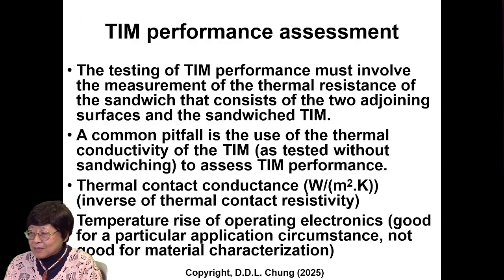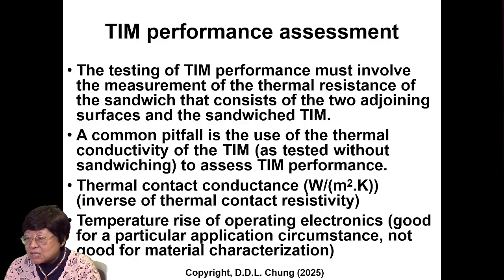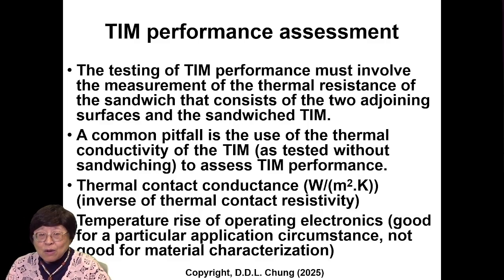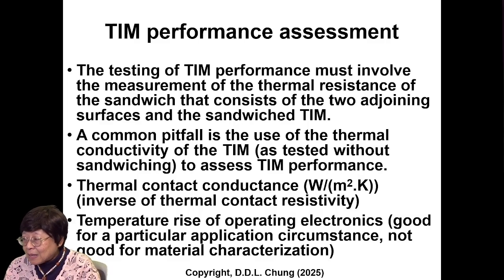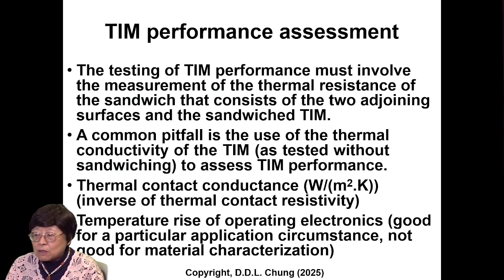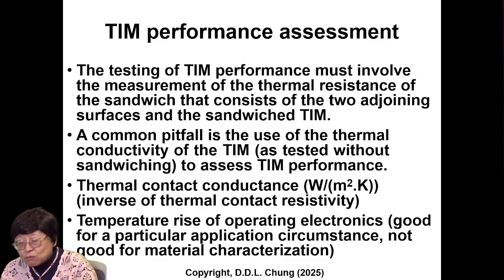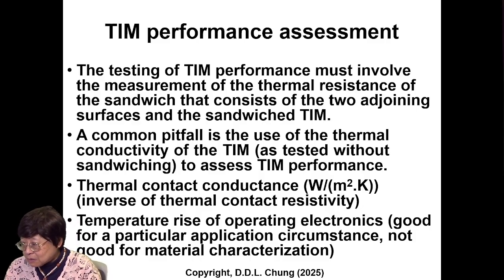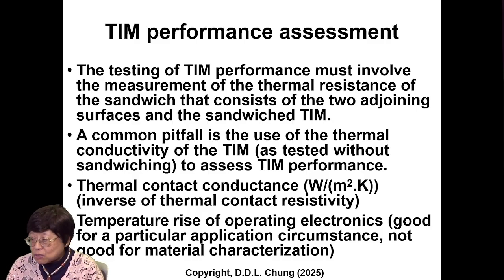Next, how do we assess the TIM performance? The testing of TIM performance must involve the measurement of the thermal resistance of the sandwich that consists of the two adjoining surfaces and the sandwiched TIM. A common pitfall is the use of the thermal conductivity of the TIM as tested without the sandwiching to assess the TIM performance. Thermal contact conductance is the inverse of the thermal contact resistivity. Temperature rise of operating electronics is good for a particular application circumstance, but is not good for material characterization.